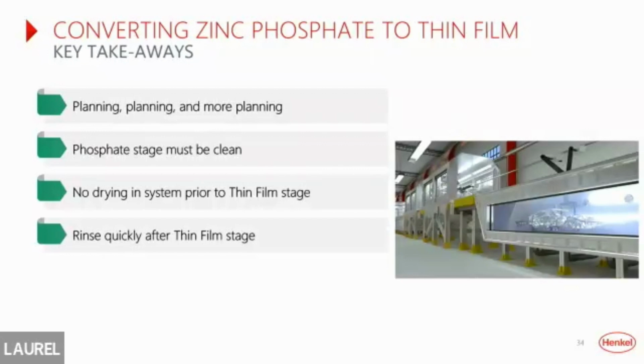Again, zinc phosphate is a self-limiting reaction. Most of us have seen the crystals on a zinc phosphate SEM. Once the surface is covered with those crystals and there's no more bare substrate to react with, the coating reaction shuts down. Not with zirconium. It will continue to build the longer it's in the bath or exposed to the chemicals.